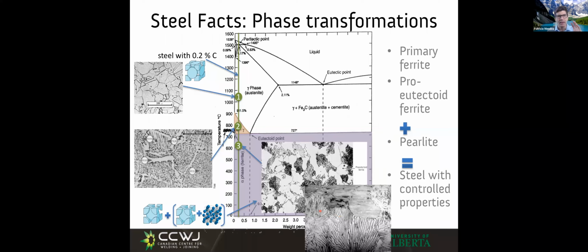Very interesting. My hope is in this slide, you start to see how you can see a structure develop. How many microstructures do we have here? We have two: primary ferrite and pearlite. How many phases do we have here? We have two phases. But let's pay attention very well to what these phases are. One phase is ferrite, the other phase is cementite. Pearlite is made of cementite and ferrite together, this lamella. So this white we see here that I'm pointing to with my marker is the same white that we see anywhere in here. That is BCC iron, ferrite. And the black is this carbide, this Fe3C cementite.